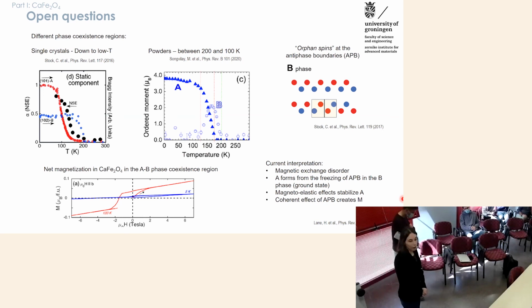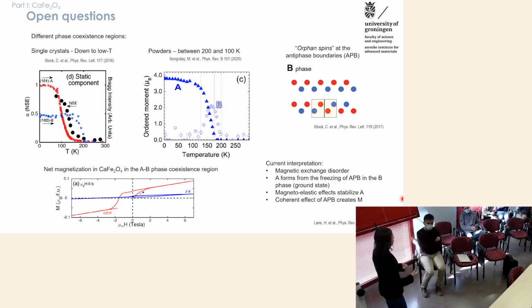And we also performed XPS measurements to try to be sure that the stoichiometry of the films didn't have any iron 2+ or other iron in metallic form, and we could never see it. So we think that actually there is not extra iron in the film.